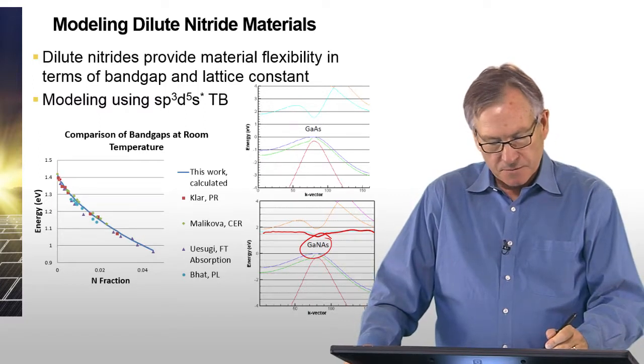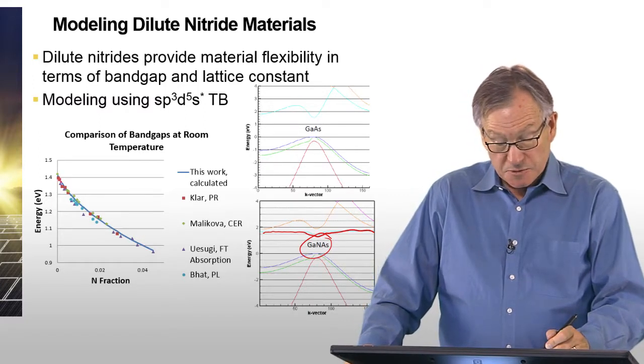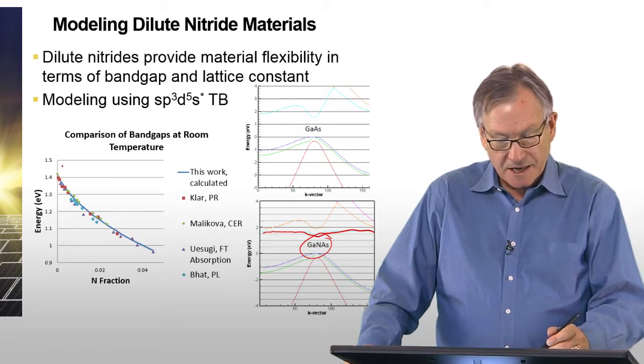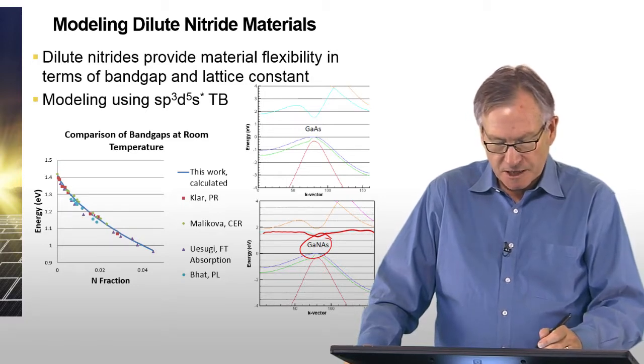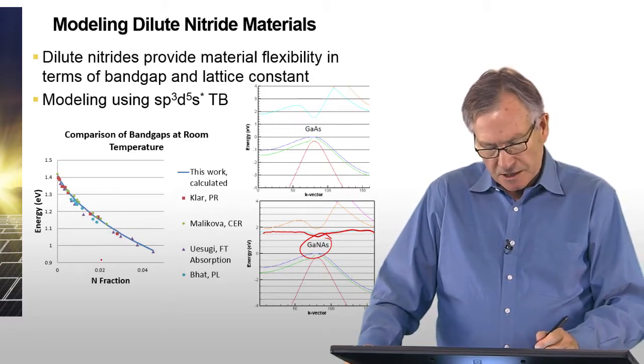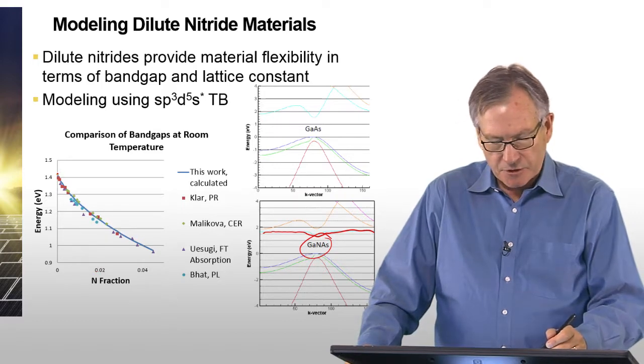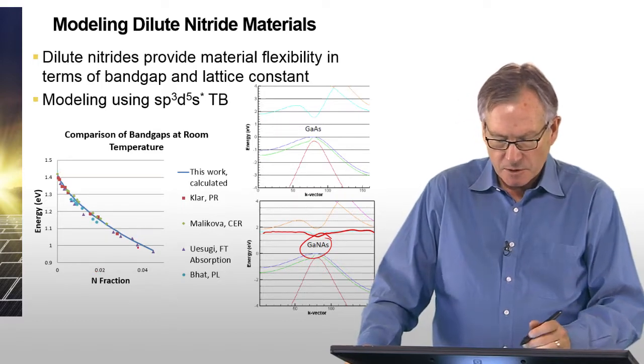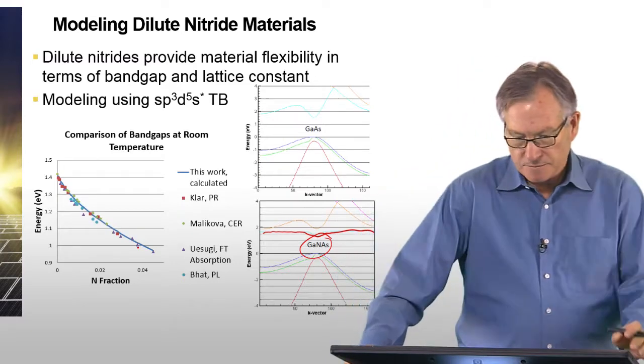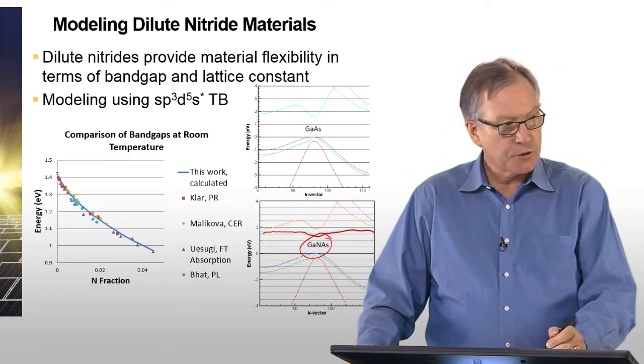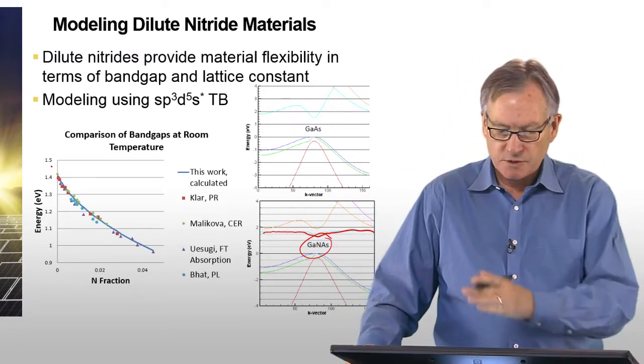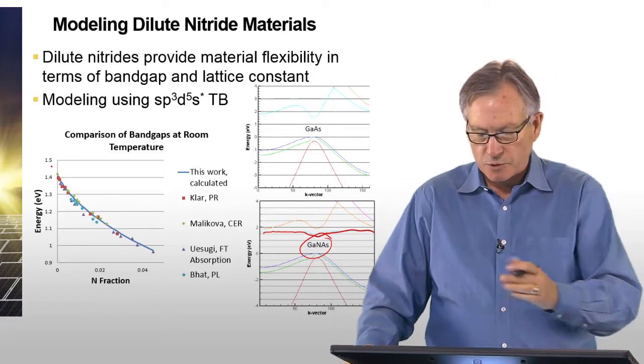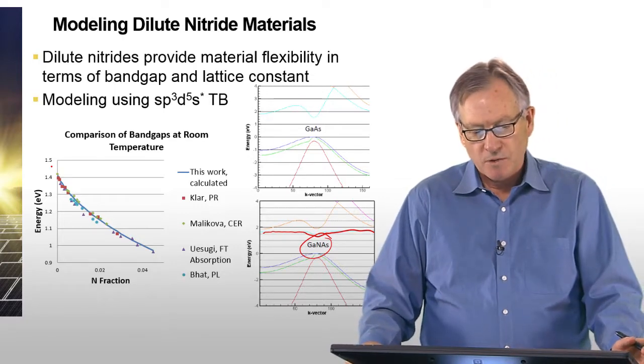This is a plot of different experimental results for the band gap of gallium arsenide nitride with different nitrogen mole fractions, and this is the calculation using the sp3d5s star method, just showing that you can get very good agreement. So this is then the approach to the electronic structure as well.